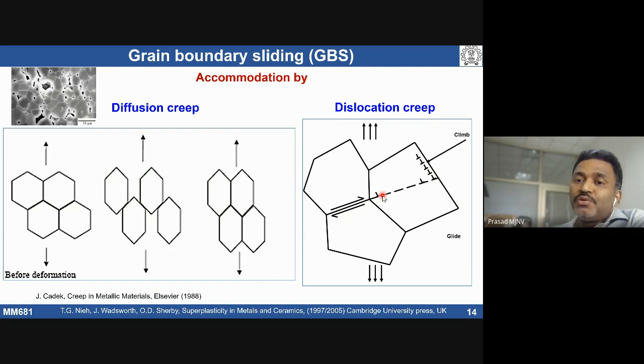So if the material has accommodation by dislocation creep, it typically exhibits large elongation, typically larger elongations than the diffusion creep accommodation. But in both the cases, even above 500% elongations can be seen by grain boundary sliding activity, but it has to be accommodated. If the grain boundary sliding is not accommodated, that can lead to cavity formations.